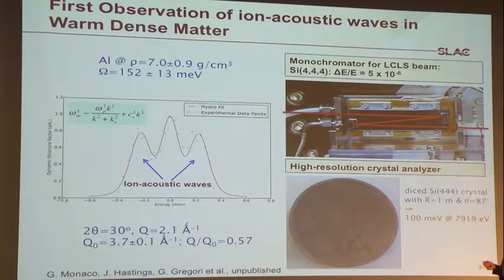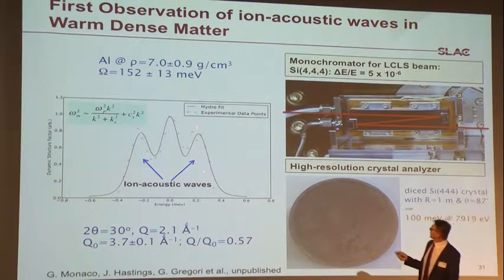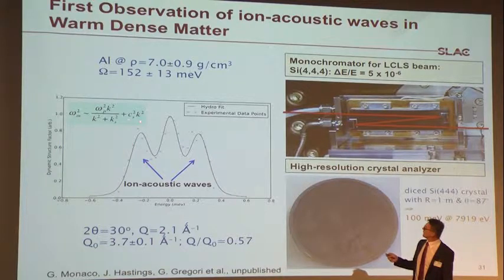let me also explain to you the ion acoustic wave measurement. That was really a brute force. In that case, we actually also use the seeded beam, but then we had to have an additional monochromator using two silicon crystals to get the energy resolution down by another 1 to 2 orders of magnitude to 5 × 10⁻⁶. And in that case, if you use a diced silicon crystal, you could observe the ion acoustic peak on either side. And in this case, it's a high K limit.